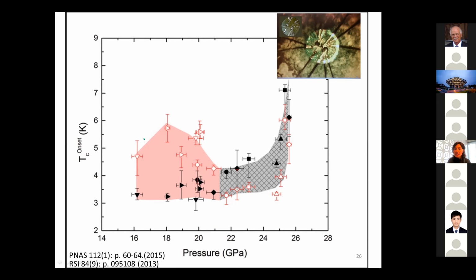We saw a difference. The red is lithium 6, and the black is lithium 7. So what one would expect is what we were thinking lithium 6 should do if you have a normal isotope effect. And instead it did this kind of thing. And the question was, what is going on?